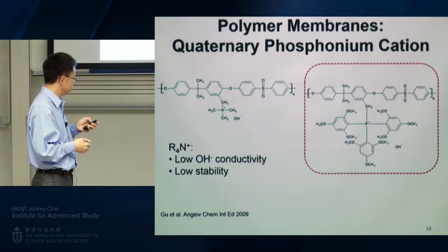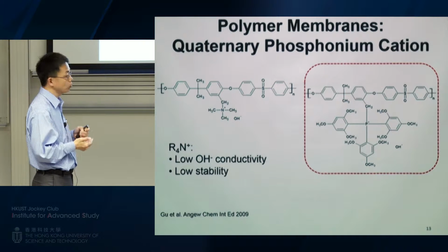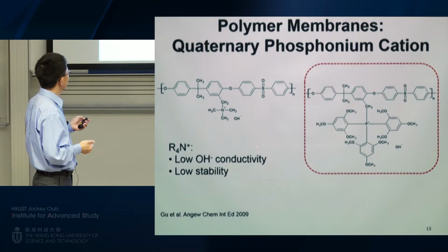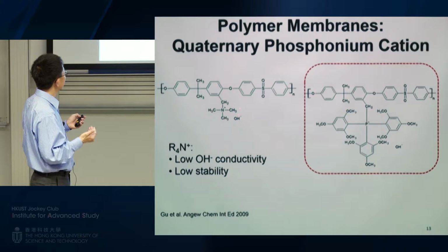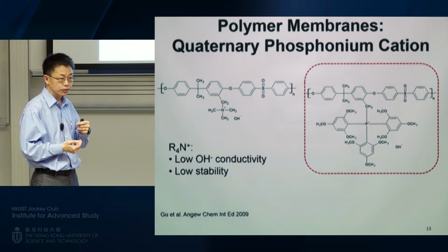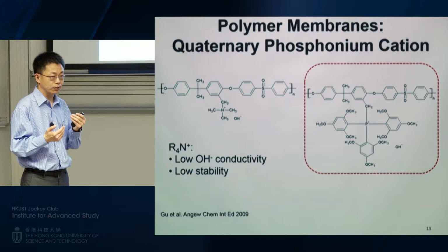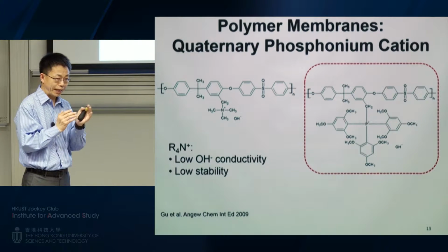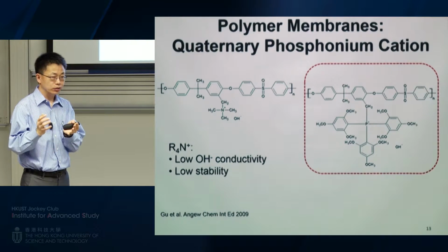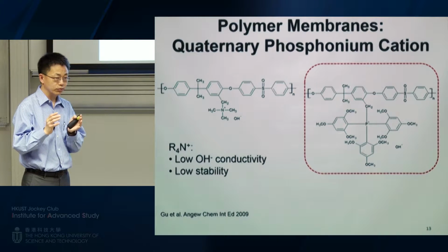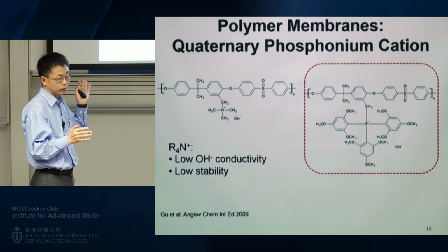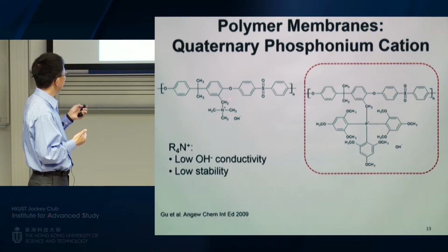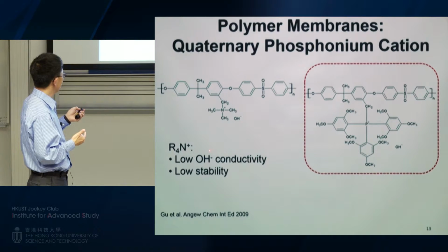So when we got started thinking, okay, we want to do this hydroxide exchange membrane fuel cell, what could we do? So we went into the literature and started searching, does any HEM exist? It turns out anion exchange resin or membrane has been there since the 1960s. Anion exchange resin means you have this cationic group attached to the polymer. You put an anion in there. You can use any anion, like chloride. But if you change chloride to hydroxide, that becomes hydroxide exchange membrane. So it's there. But the problem is they are all quaternary ammonium based. So you have this nitrogen sitting in the center with a positive charge. And this turned out to have low conductivity and, more importantly, low stability.